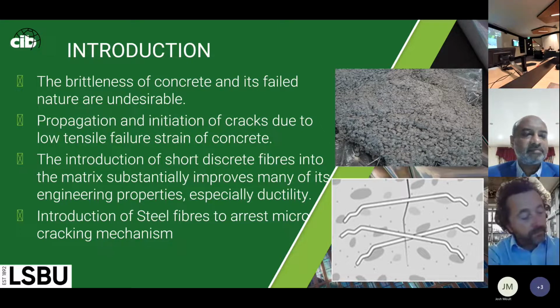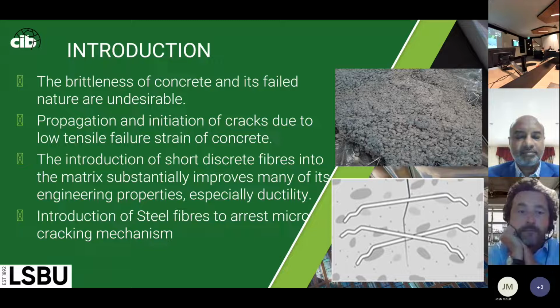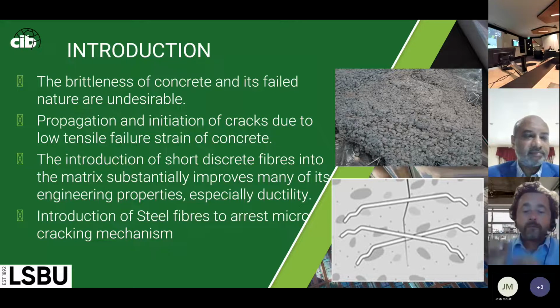Micro is very tiny, we can't see it with naked eyes, but when it becomes macro, we can see it, and that's what causes failure. So the introduction of short discrete fibers into the matrix substantially improves many engineering properties of concrete, especially ductility and durability. This is just to arrest the cracks. When a crack is initiated and bridged by these fibers, it stops. Even at initial cracks, there could still be post-cracking capacity of the structure.